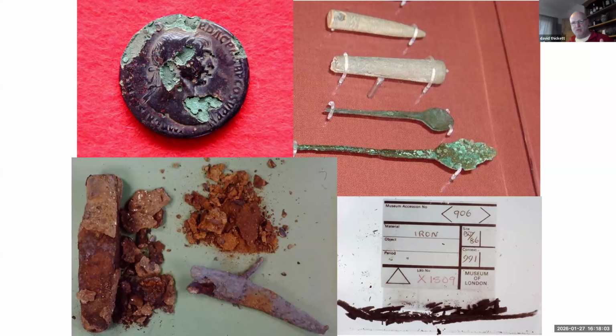They've been sat in the same showcase for quite a few years. One of them is very badly corroded. One of them is apparently perfectly stable. And if we can identify which of the objects are stable and unstable, we can then tailor the preventive conservation for them. We obviously need to do something for the bottom spoon, keeping it at very low relative humidity. That's quite intensive in work. The top one, we probably don't need to do anything beyond putting it in a showcase so nobody actually walks off with it.